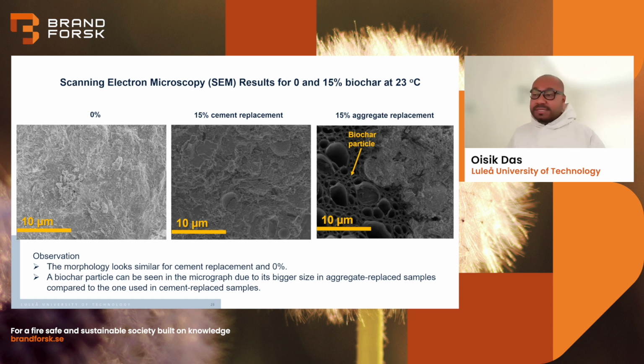We have chosen 15% because, like Rhoda said previously, the 15% biochar added concrete had similar mechanical properties. So we have chosen this sample because this is the highest amount of biochar we can add in concrete and still have the same mechanical properties. So it's the best according to us because the more biochar we can add in concrete, the more sustainable it becomes without losing mechanical properties. That's why we have chosen 15% as our optimum replacement or loading amount of biochar.